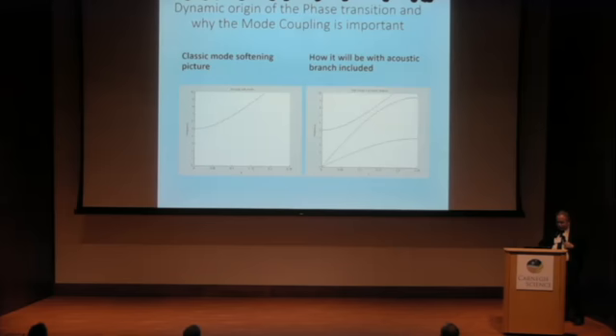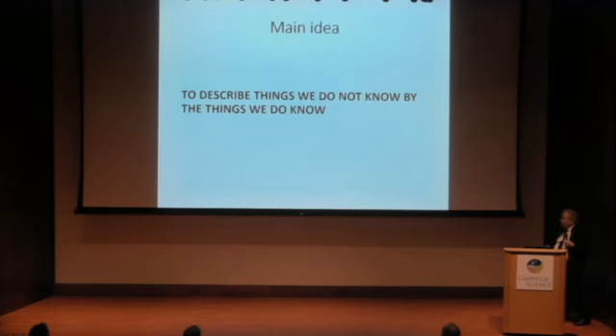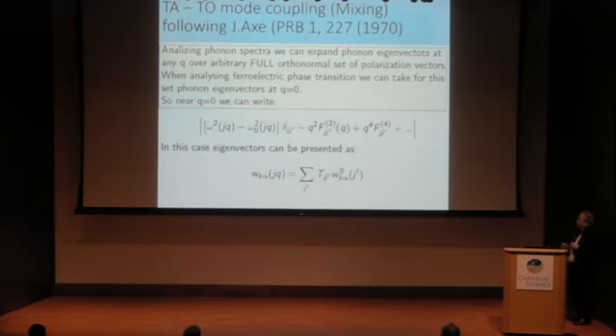it looks like this. The mode just softens, but now let's consider that we do have acoustic on its way. Depending on the slope of acoustic, we can have two situations. If the acoustic is a very low one, nothing happens. If the acoustic is rather high, then they cross. And we do not expect any crossing for the modes that have the same symmetry, like it is in perovskites, where the optic and acoustic have the same symmetry at finite Q. So I'll go through the main idea of the old paper of Axe and Shirane.